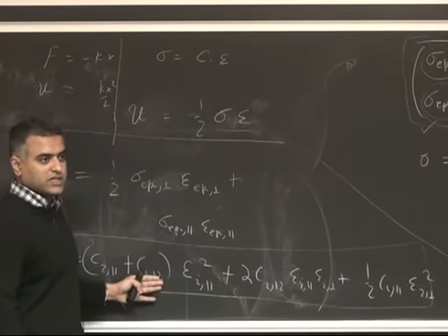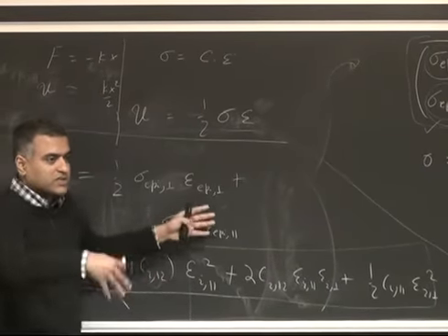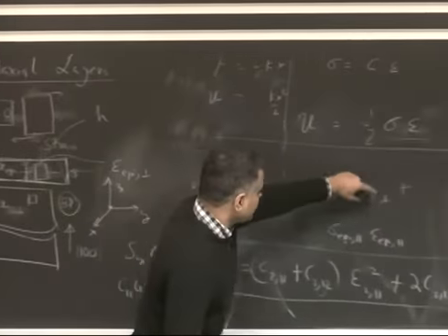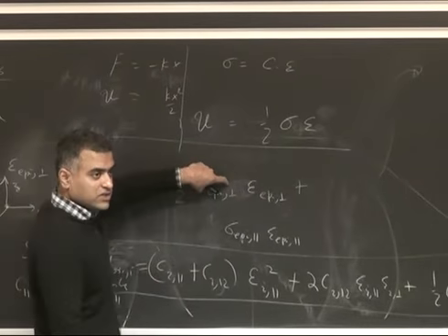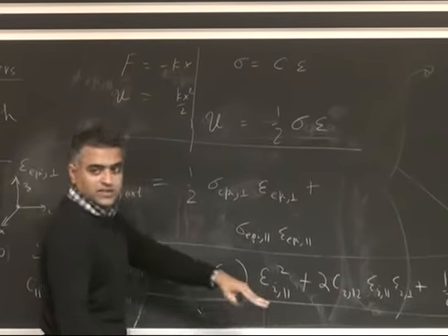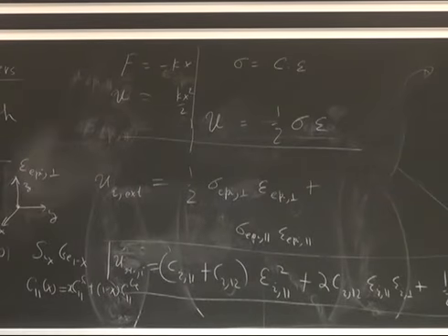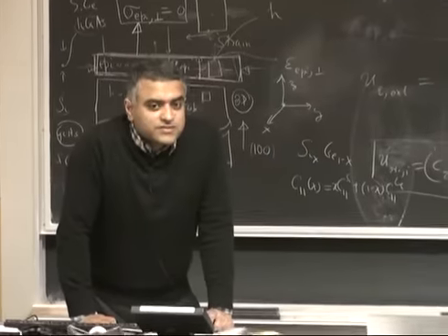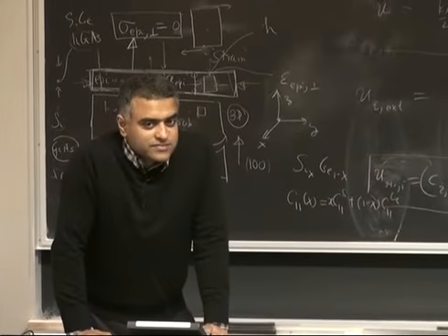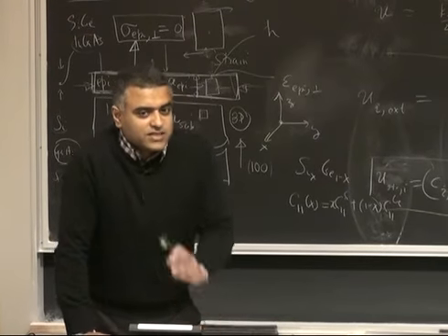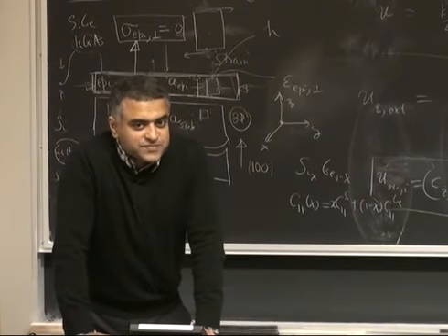Now you have only strains here. Right. So if sigma perpendicular, if this term is 0, and you plug values in for all the others, you will get this. You have to be careful because the strain in the parallel direction determines the stress in the parallel direction and the perpendicular direction due to the Poisson effect. So exactly right. You will have a non-zero value if you're controlling the strain, which is what you're doing a lot of times.